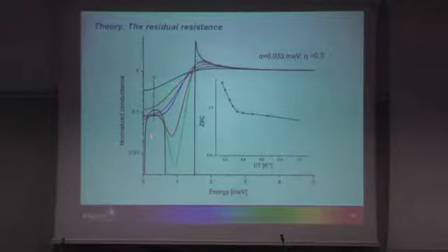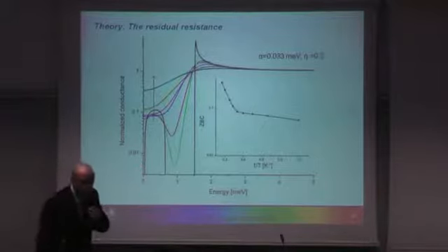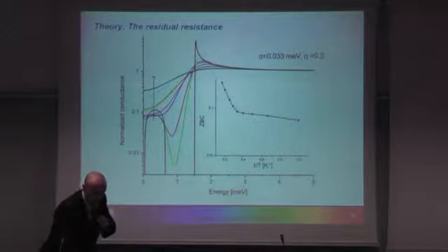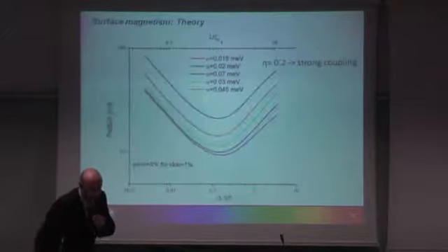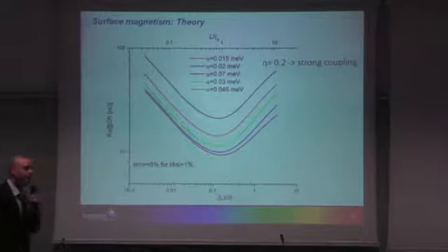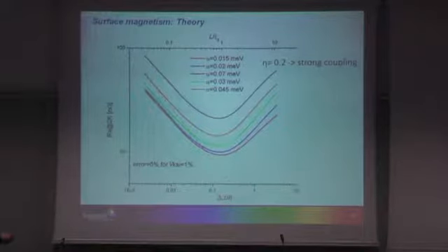However, if we decrease slightly the value of eta closer to the Fermi level, and we increase alpha slightly, so this is larger as compared to the previous peak, then you start to see a saturation when you decrease in temperature, which strongly reminds of the residual resistance. So, okay.